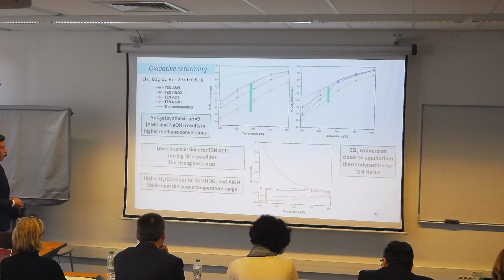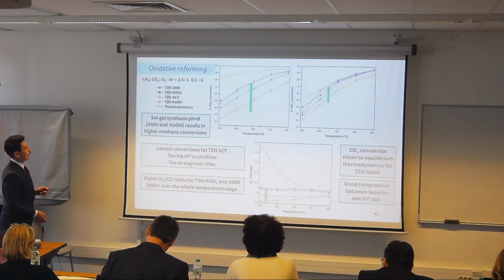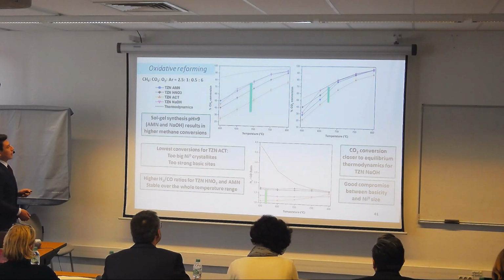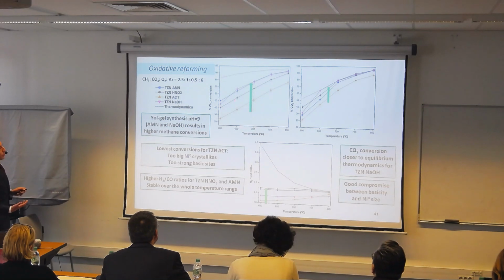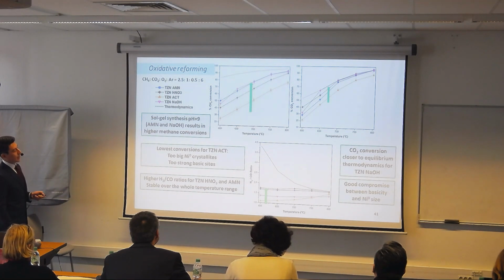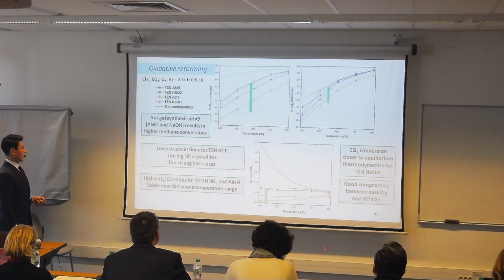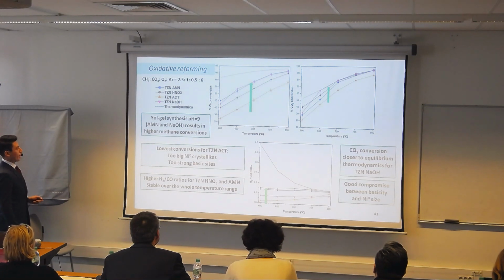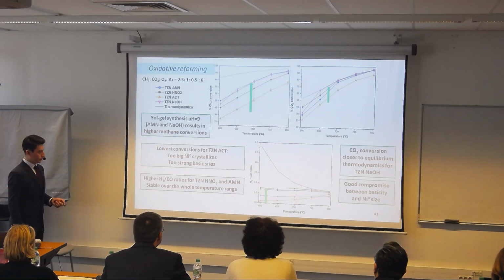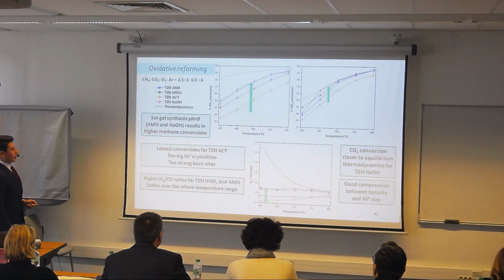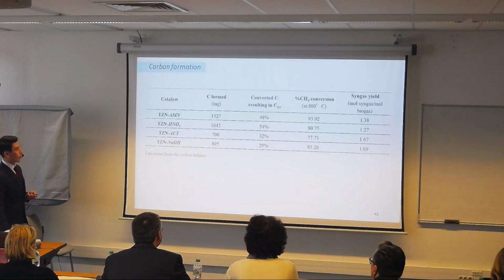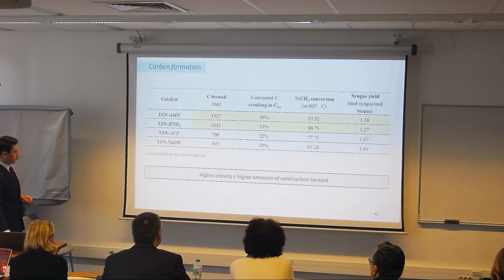Moving to the oxidative reforming, we can see that the sol-gel method enhances the conversion compared to the previous one. We have here the previous catalyst, and all of the modified ones have a higher conversion for methane and CO2. We can say that the problem was that we had too big crystal size and too strong basic sites. Also, we can see that there is a good compromise between the basicity and the crystal size when we are working with the reforming of biogas.